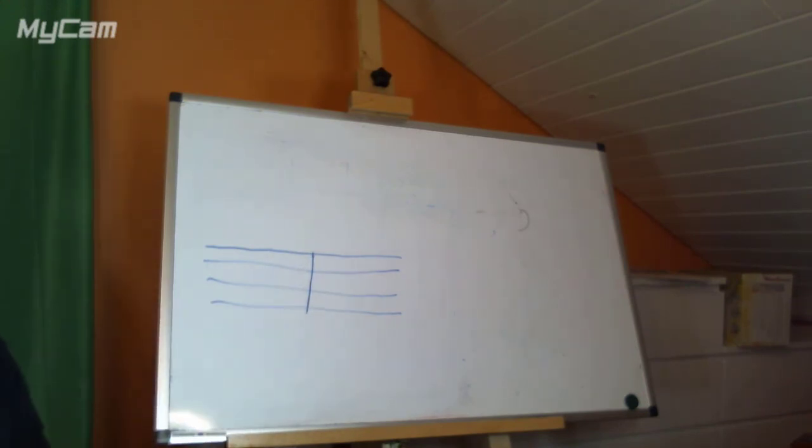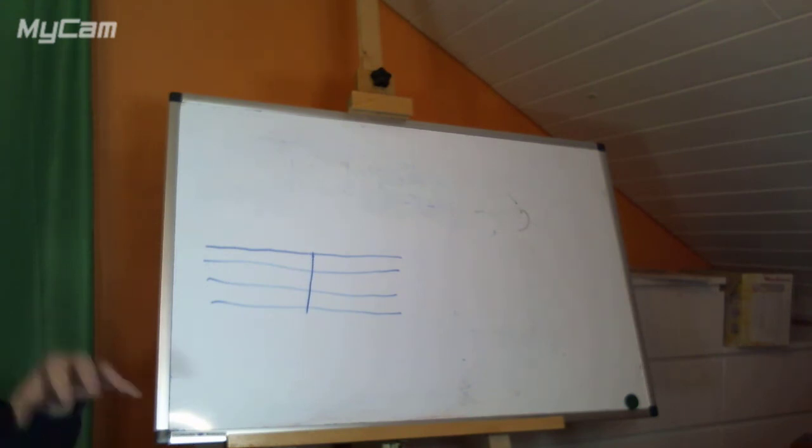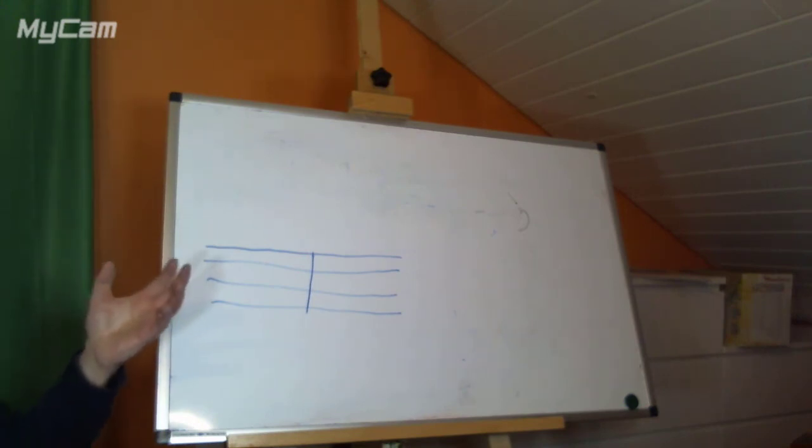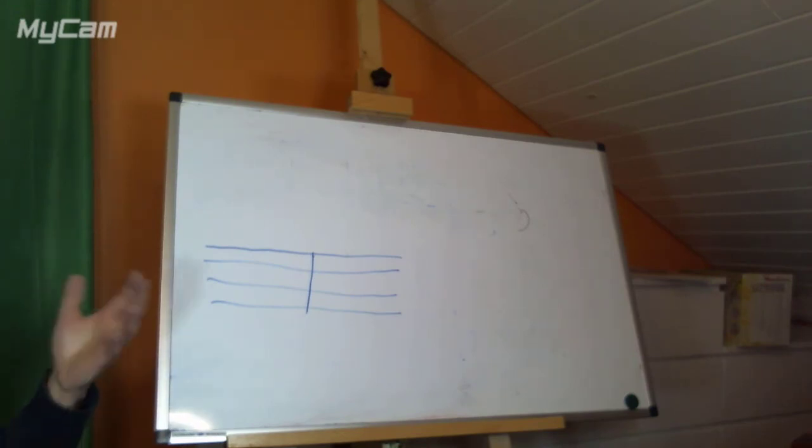The problem being that they also grow very fast. So it works in both directions, but obviously that's going to mean that if we have a spiral defect to start with, that will grow preferentially to the rest of our material. And that means that when we try to etch it, it will etch preferentially to the rest of our material as well. And so that can be a bad thing, and it can be very difficult to avoid,